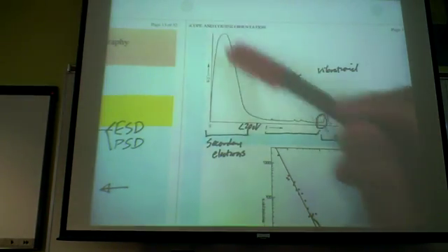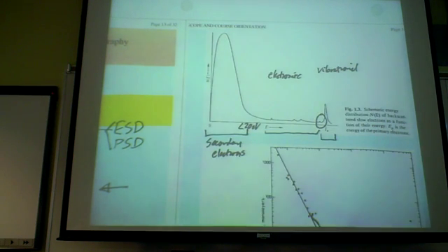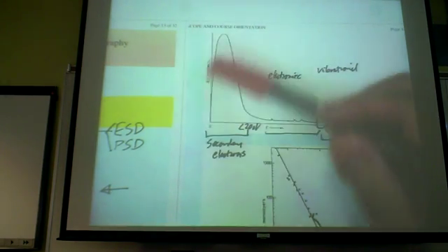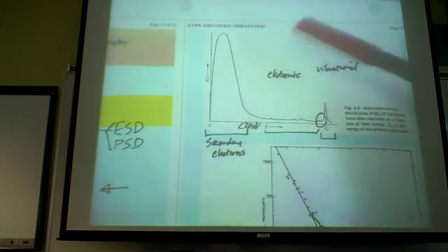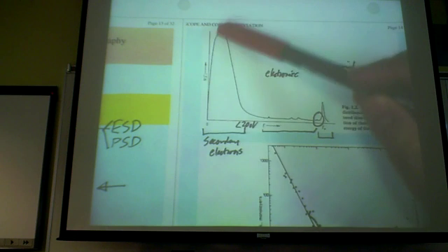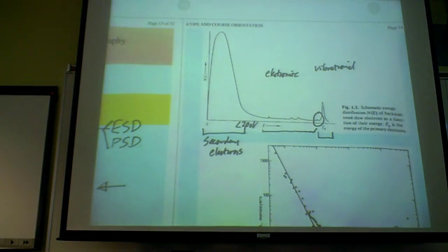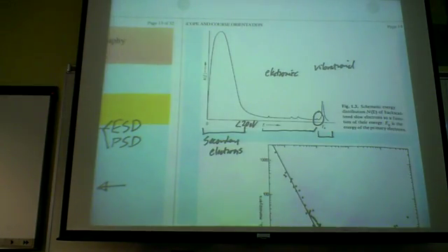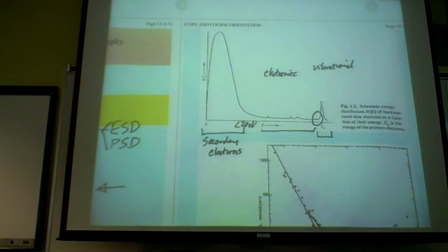So they are really very nice if you can detect these secondary electrons, because they are reflecting what's on your surface, the contour of your surface, and this is really what electron microscopy is all about. As we'll see a little bit later on, if you can detect these secondary electrons, you can see the morphology of the surface structure, if you like, of your surface, because these electrons emit from near the surface.